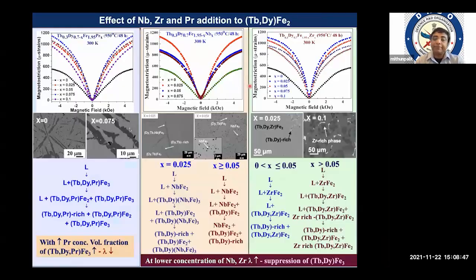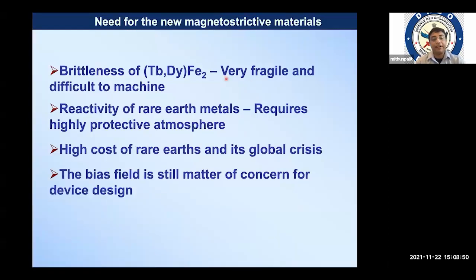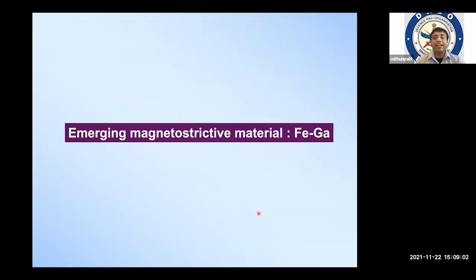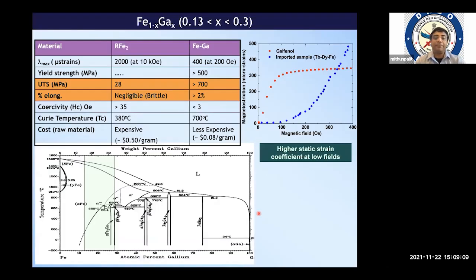So therefore, to undertake this challenge, especially for the actuator application, we thought it is better to identify an alternative material which does not have rare earth and which has a very sharp magnetostriction versus magnetic field curve. So accordingly, we searched for different materials, did different calculations and found iron gallium as one of the great alternatives. This iron gallium material has very good ductility, much better ductility compared to RFe2 material. Of course, it is not a structural material.